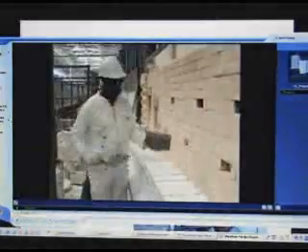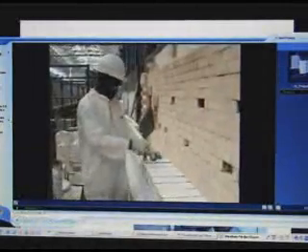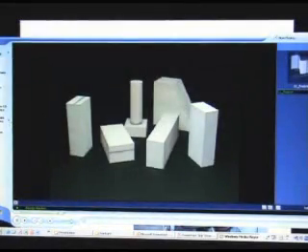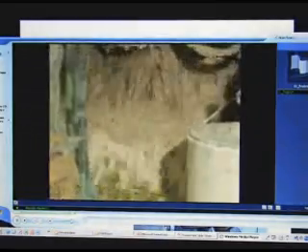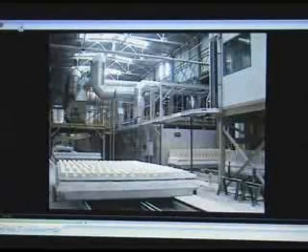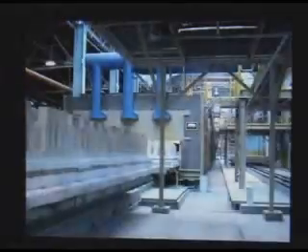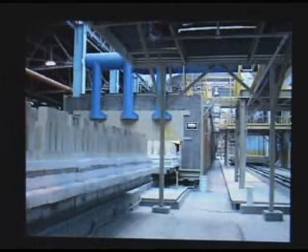Thermal Ceramics has been the market leader for insulating firebrick for more than 60 years. The lower temperature grades K20 through K26 are individually manufactured by our unique slurry casting operation. We then fire each cast brick in a new precision-controlled tunnel kiln at or over its use limit temperature. This guarantees proper heat treatment and ceramic bonding throughout the brick, resulting in high hot strength and low shrinkage. After firing, these bricks are machined to precise dimensions by processing through a series of grinding wheels.